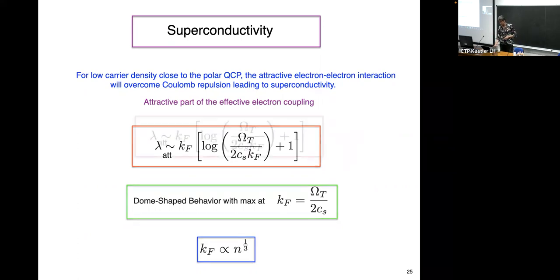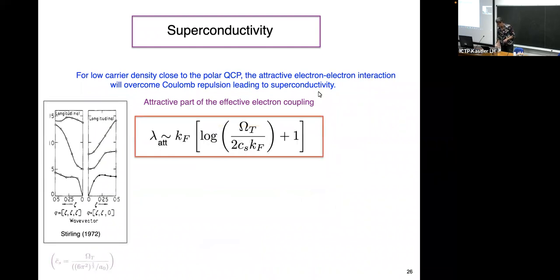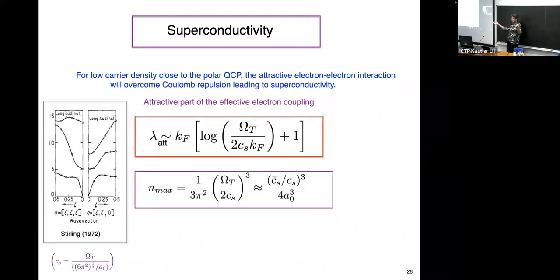So what do we get in terms of the maximum? Where's our maximum in terms of density? Well, this is why it's important that we are looking at K vectors across the Brillouin zone, we can look at the dispersion. Of course, we just consider a very simple quadratic dispersion, but in strontium titanate, it's very steep and goes like this. So when we calculate the cutoff to the optical phonon, we don't just take the speed of sound from here, we actually do a Debye average over the whole Brillouin zone. And you'll see why that's important, because n max then is going to be CS average over CS.